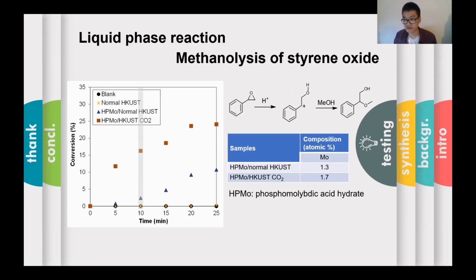So note that the reaction rate of the styrene oxide methanolysis over these two samples was normalized by the molybdenum loadings. This result shows that the HPMo loaded HKUST CO2 has better reaction kinetics than the HPMo loaded normal HKUST, which might be due to more accessible macropore structures in these materials. So we also have demonstrated that the macropore structures in HKUST MOF produce a greater improvement in catalytic performance of the liquid phase reaction when compared to the gas phase reaction. This result is evidence that the macropores may be beneficial in overcoming the diffusional limitations, which are more prevalent in liquid phase reactions than in the gas phase, and have a greater effect on reactions where bulky molecules are involved.